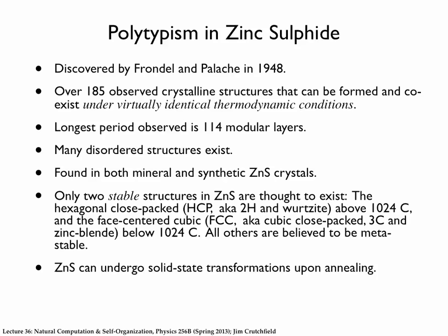Now, if these are layers, these layers are hard to move around. Even though they have degenerate energies, they can't slide over each other relatively easily. You're still moving an entire layer in a crystal, so it doesn't happen just willy-nilly. But if you heat them up enough such that their structure is no longer the stable structure, and there's another structure that would be lower in free energy, then these guys will try to slide to transform to that.